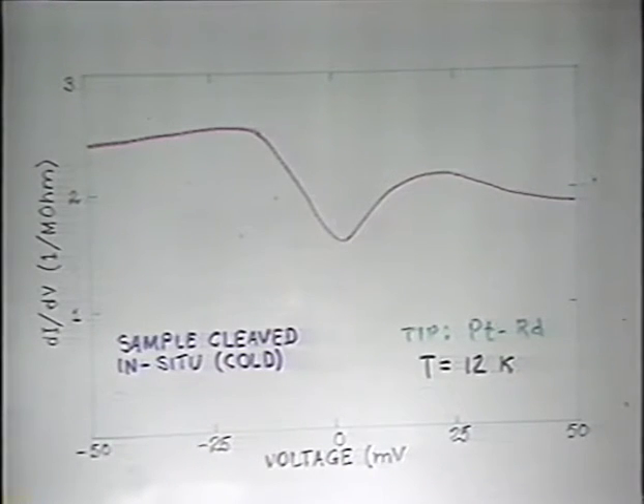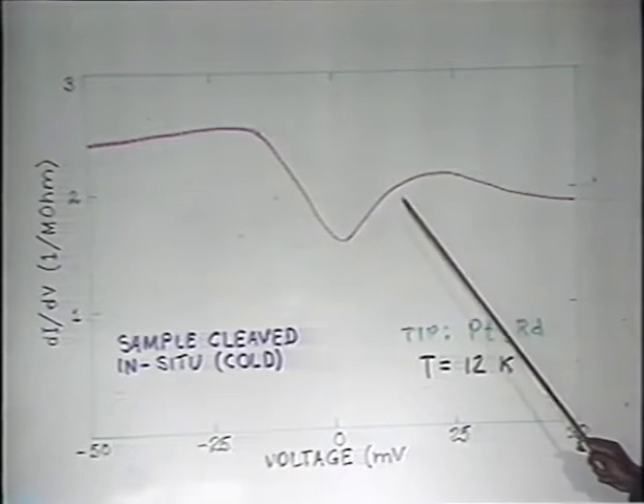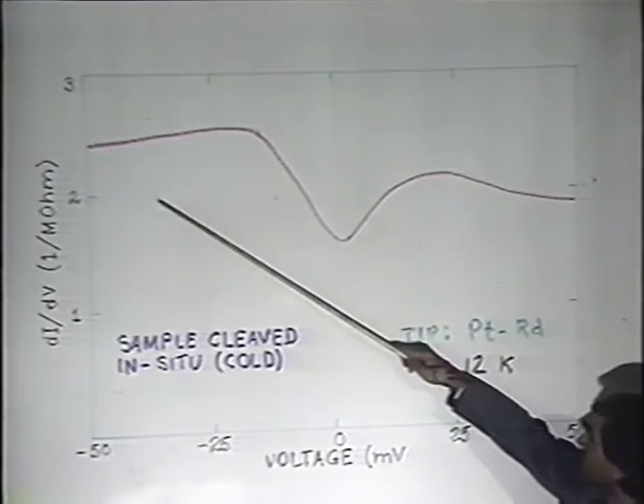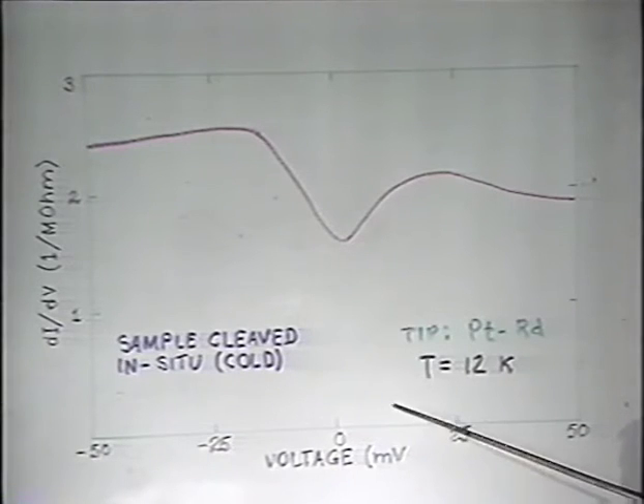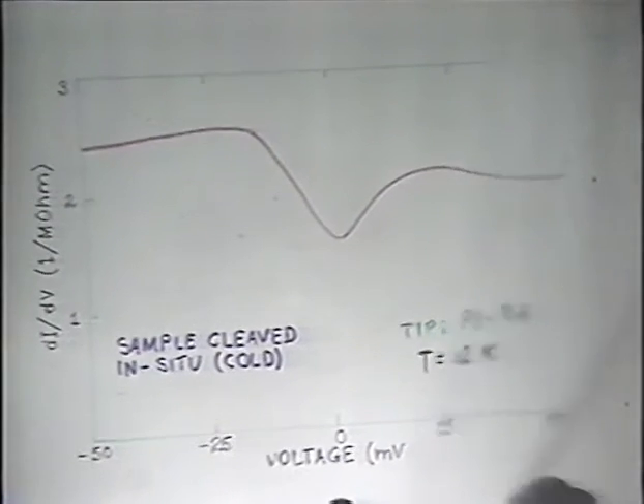One might ask, well, why are these curves so washed out? Why don't I have a nice peak and a drop to 0 here and a nice peak on this side? The one thing that is quite different in tunneling microscopy is that it's very common to achieve very high current densities in this type of tunneling. It's very easy to get above 10 to the 6 amps per square centimeter under the tip. In that situation, you can clearly have some depairing, and that can definitely wash out the IV curves.